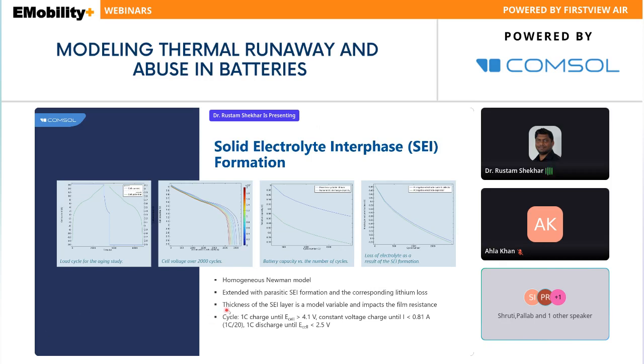So in that case, the thickness is a variable, and then we can perform one CCCV condition where we have a constant current charging up to the 4.1 volt, and then we can discharge it down to the 2.5 volt. So this way we can keep on charging and discharging the cell, and then observe the comparison of the discharge curve